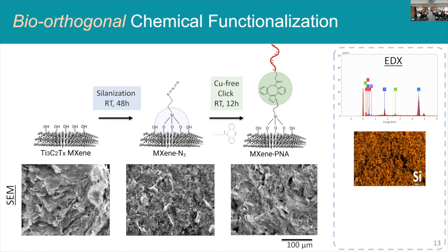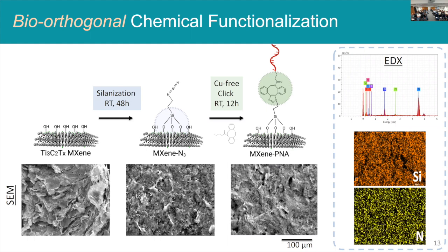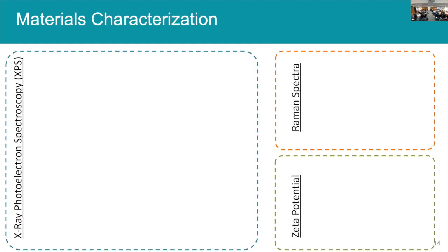And you can also look at the elemental mapping on EDX. You can see where these elements are popping up on the surface, and you'll see that we get a very nice homogeneous distribution of silicon everywhere, which is wonderful. This is what we want. Also, nitrogen is everywhere on the surface, very nicely homogeneously distributed. We did a lot more materials characterization. I'll show you a little bit more of what we've done.